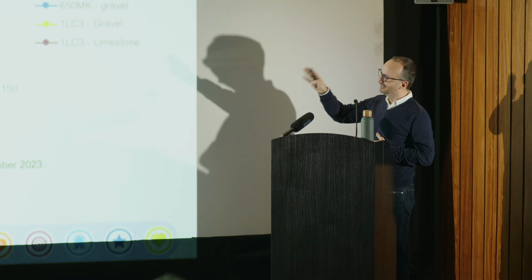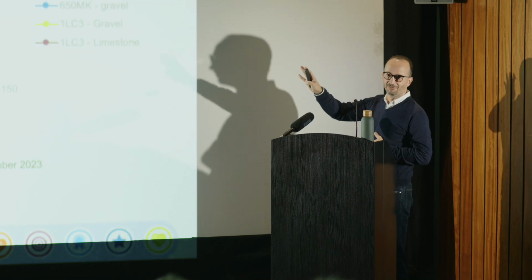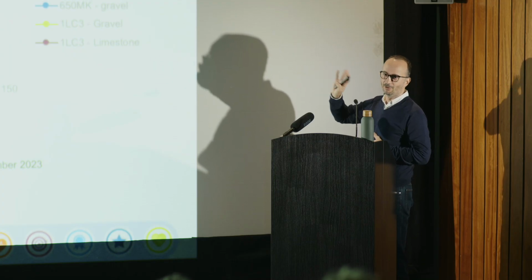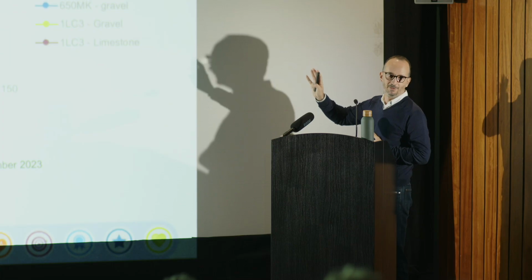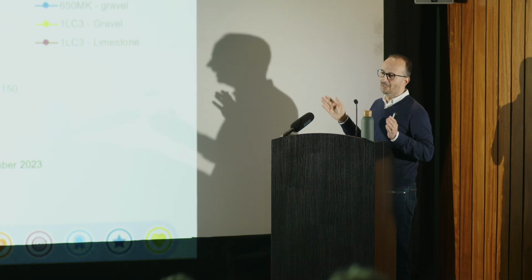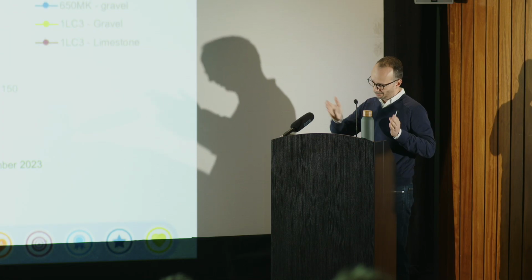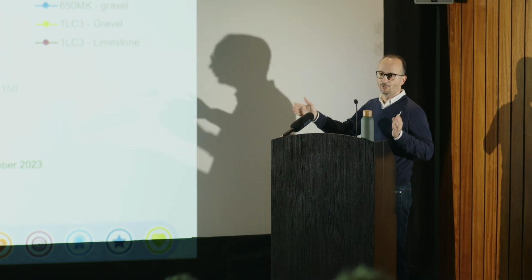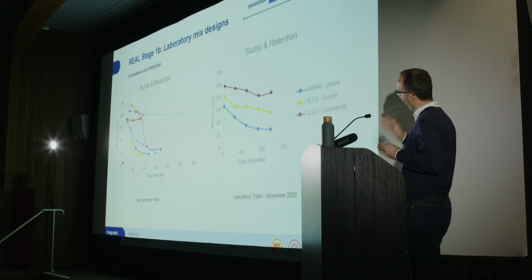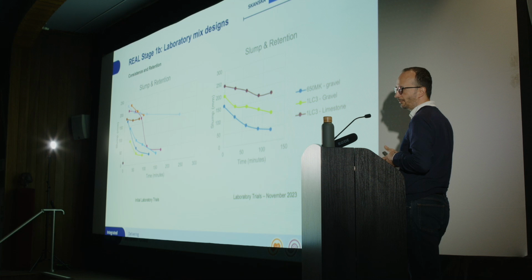The left-hand side is a mess. So this is the first phase where we couldn't get it to work more than 15, 30 minutes maximum. Bear in mind that from batching concrete to placing it, it might be an hour, 2 hours sometimes maximum. We couldn't use that. We would lose the trucks on the way in.